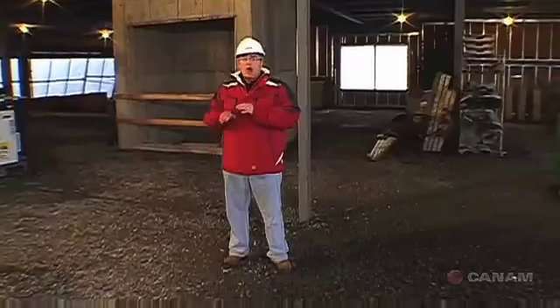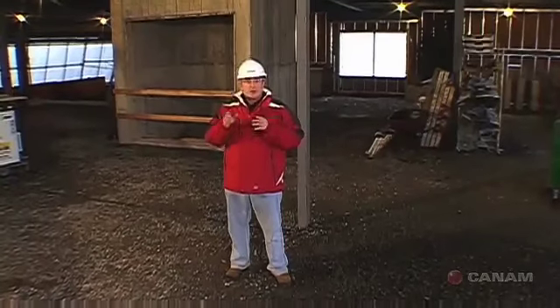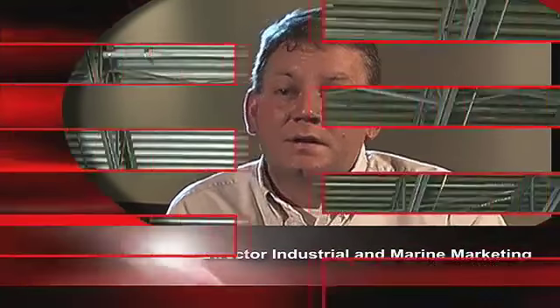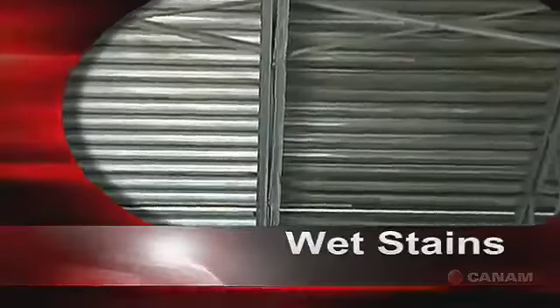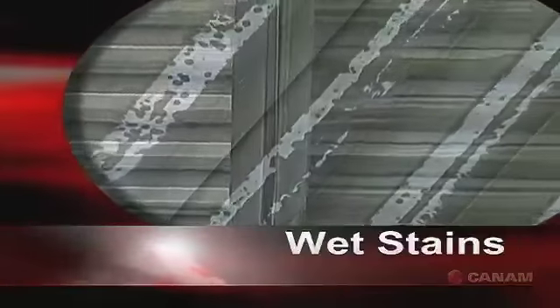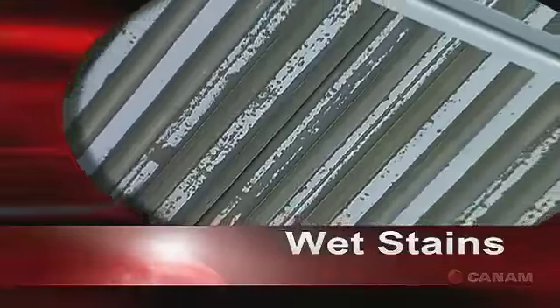So, why does deck staining still sometimes occur with all of the quality controls in place from Can-Am and their suppliers? When the galvanneal steel is exposed to high humidity environments for an extended period of time, it may exhibit some staining. These stains may be red rust, white, or even black. This means that there's been some surface oxidation, but it does not affect the integrity of the zinc-coated steel. This is generally called wet stains.